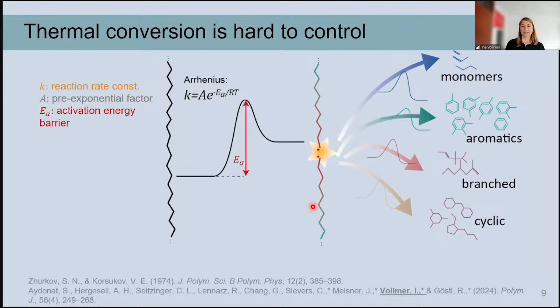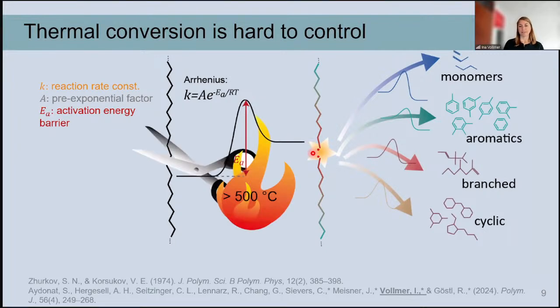So the reason for that is that these carbon-carbon bonds require quite some energy to be broken. So there's this barrier that has to be overcome to cleave these bonds. And this is why we need such high temperatures. But at these high temperatures, we can also not suppress the follow-up reactions of the cleaved polymer, because these activation energy barriers are also very easily overcome. And this is why we get such a mixed and invaluable product.